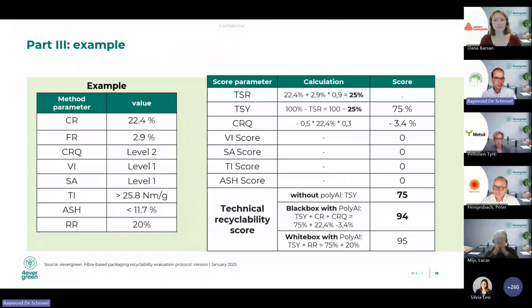An example. Coarse reject is 22.4, fine reject 2.9. The level of coarse reject quality is okay. So there's no penalty for visual impurities, no penalty for sheet adhesion. The tensile index is above the 25.8. That's the threshold that was measured using a database. The database is still increasing, but with the data we had, we say that this is the threshold for the tensile index for liquid packaging cartons.